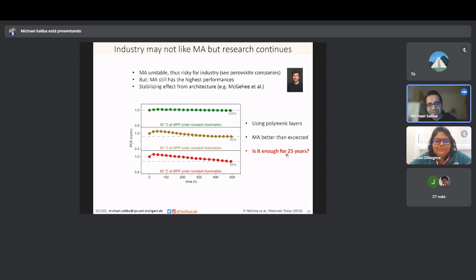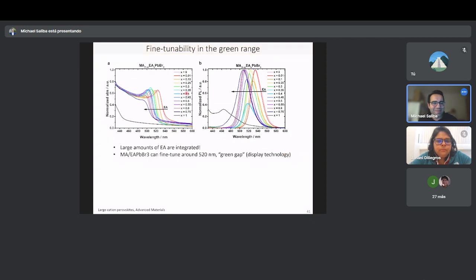So this brings me to my last point in this segment. So I talked about mixing with smaller cations with rubidium and cesium, for example, but also it's of course possible to mix with larger cations as well. And we tested guanidinium, ethylammonium, and imidazolium, and we found with theory from Filippo De Angelis that only ethylammonium, because of its mischaracterized cationic radius, so it's smaller than literature assumed previously, that only ethylammonium can successfully be mixed with methylammonium. You see that here, and it shifts beautifully the band gap through the green, which is exactly the area that is important for display technology. So we made devices from it.